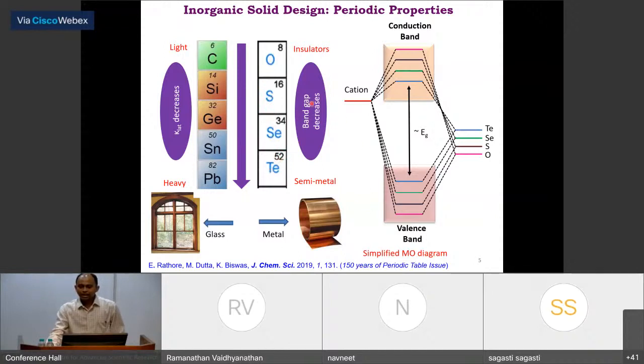And you can understand this decrease in band gap by this simple molecular orbital diagram, where the electronegativity actually decreases from oxygen to tellurium, so that the atomic orbital shifts up and the gap between HOMO and LUMO decreases. Now in an extended system, basically the band gap decreases, and band gap goes even to 0.2 to 0.3 electron volt in metal telluride. So we can dope them heavily and can achieve metal-like conductivity.